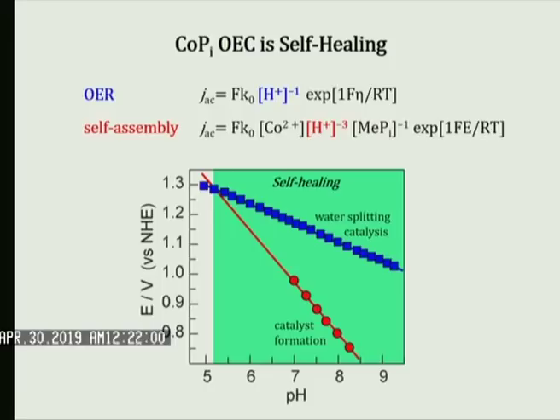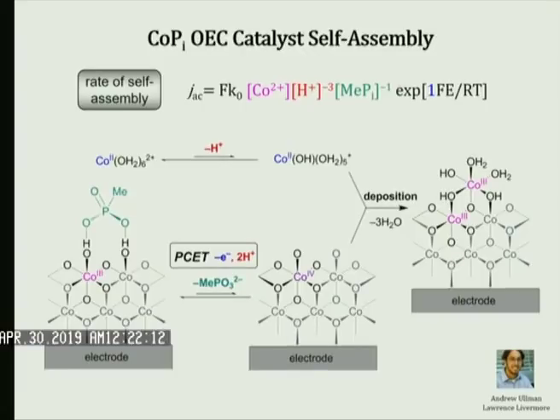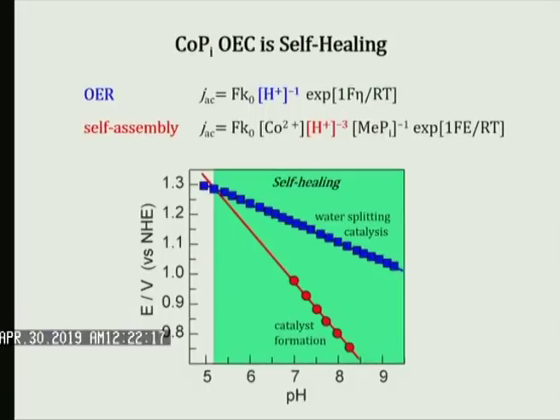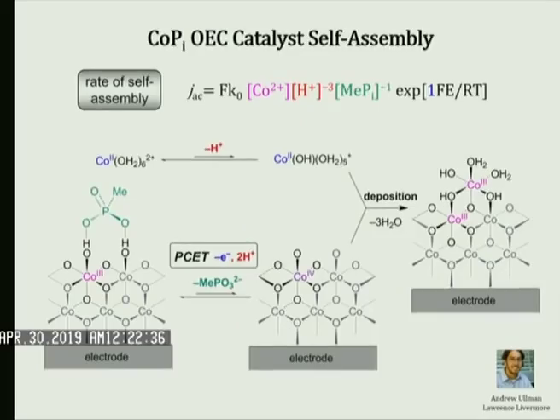I split water, so I have to apply a voltage to my catalyst to split water. I split water at 1.2 volts at pH 7. But to run Andrew's cycle for the self-assembly of the catalyst from solution, I only need at pH 7, 1 volt. So as long as I'm splitting water and making oxygen, if the catalyst falls apart, I have plenty of extra voltage to drive this self-assembly process.